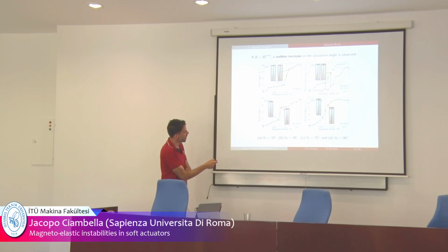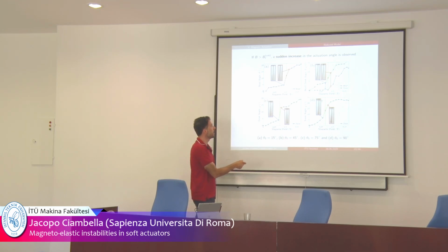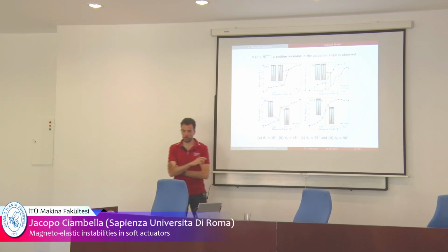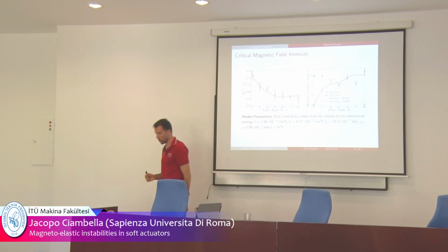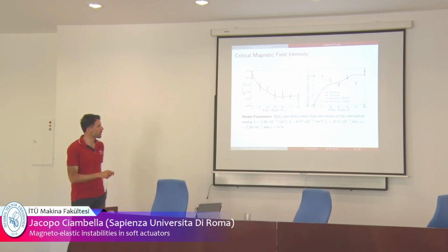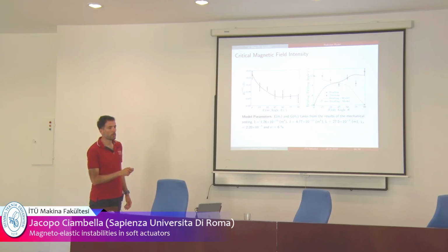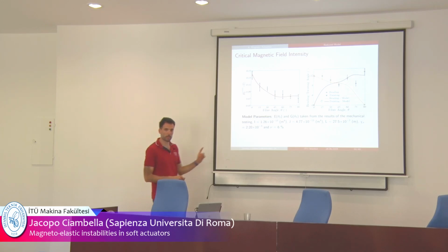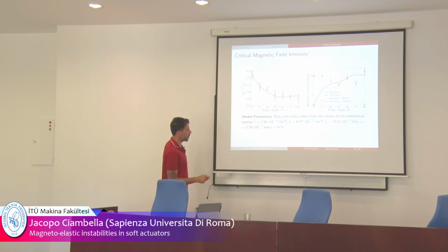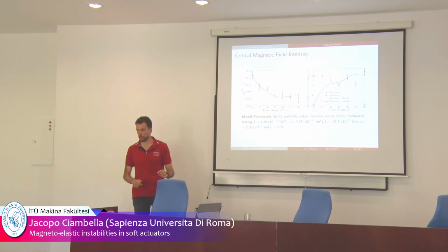The same happened for this, which was 50 degree, 45 degree, 75 degree, 90 degree. In 90 degree, you also always see this jump in the deformation, but you only observe twisting, very little bending. And so these are the fittings with the model. You can see here the critical field in terms of the initial fiber angle. These are the experimental results, and this is the prediction of the model. I should say that it works quite well in predicting this behavior. And again, the model works pretty well in predicting also the bending and twisting angle. So the yellow line is the bending angle predicted by the model. This is the twisting angle predicted by the model, and the dots are the experimental results.